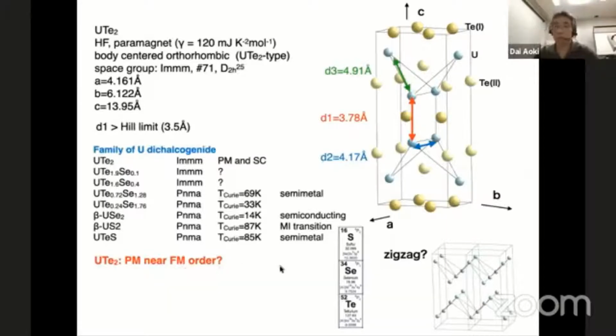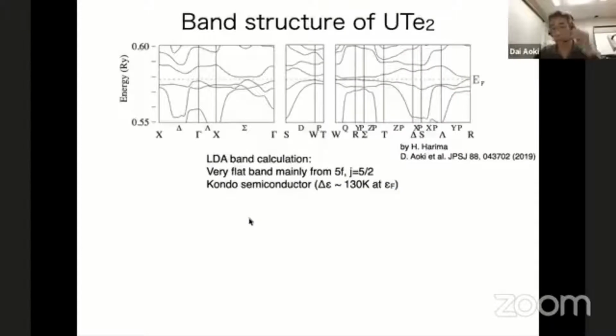Before going to the superconductivity, I want to show you the normal state or some basic properties. This is a band structure calculated by Professor Harima. Here this red dotted line is the Fermi energy. You can see there is a small gap at the Fermi energy, and the band structure shows a rather flat band near the Fermi energy. This is calculated by LDA. The LDA band calculation shows a very flat band, and Kondo semiconductor-like behavior, small gap and flat band.